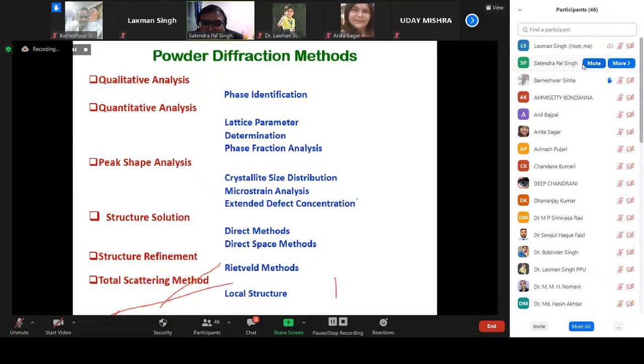That means if there are various phases or mixtures of phases present, we can do phase identification, and also quantitative phase analysis: what is the fraction of those phases? And what is the lattice parameter? What are the contents of the cells? And we can do peak shape analysis. That will give us the crystallite size distributions and microstrain analysis, and using this powder XRD